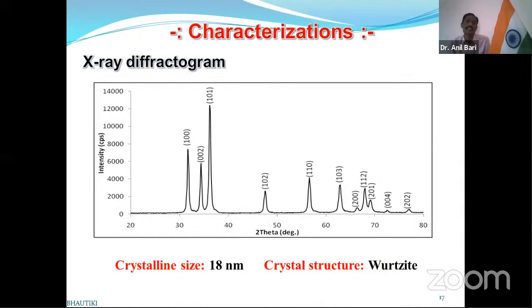Then we can characterize this powder with the help of X-ray diffractogram. This is an X-ray diffractogram of a typical prepared zinc oxide nanopowder, and the crystal structure is about wurtzite and the size is about 18 nanometers. We can calculate the size by using the Debye-Scherrer formula, and the broadening of the peak shows that the prepared nano powder should be nanocrystalline in nature, so it is 18 nanometers in size.